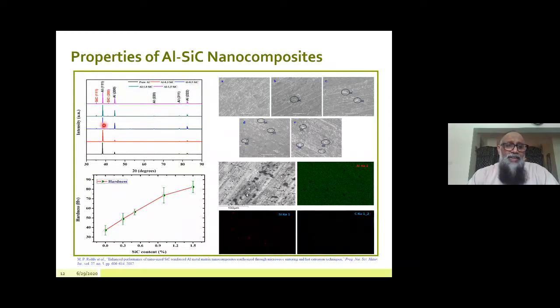We can see these XRD spectra are very crystalline because of the crystalline nature of the aluminum matrix, and we can see that with increasing amount of silicon carbide, the reinforcement peaks are also introduced into the structure. It means that the silicon carbide as a reinforcement has been introduced into the matrix. And these are the SEM images of the developed nanocomposites. We can see that the silicon carbide is incorporated into the aluminum matrix, and this is the EDX analysis showing the distribution of silicon carbide in the aluminum matrix.